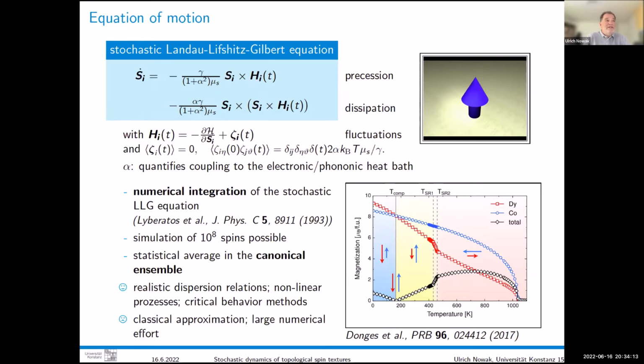So our effective field here, which is the gradient of the Hamiltonian with respect to the spin, also contains a random component, a noise component, zeta of t. And you can calculate the properties of the noise. Here we use that the average is 0, and the correlations look like that. So it's a white noise, and the strength of the noise is given by the damping constant alpha that appears here in the dissipative term, and also by the temperature.